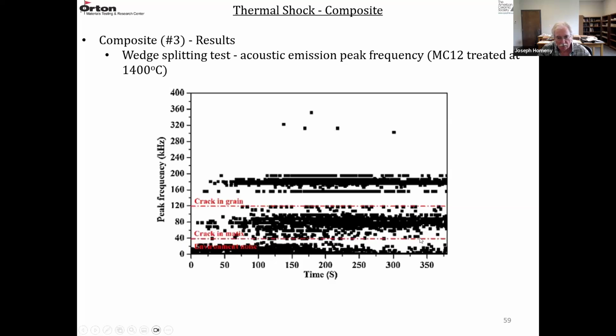So on this curve are the peak frequency versus time during the wedge splitting test. This first dotted line here in red, anything below that line is just background noise. And then below that second dotted line, in this region between the two dotted lines, those acoustic emissions are characteristic of a crack propagating in the matrix. And then above this other line, the top red line, these peaks are characteristic of a crack propagating in a grain.